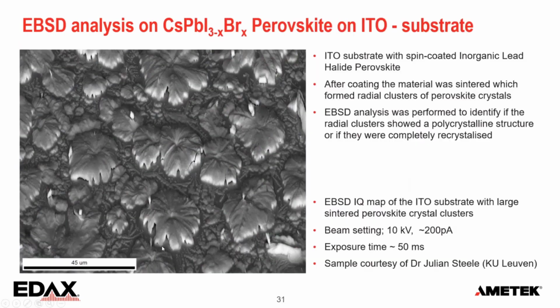Now, another one, this was a little bit more tricky. This is an ITO substrate with fibers of inorganic lead halide perovskite on top. And then it was sintered. And during the sintering, these fibers are merged, they're fusing, and they are producing these flower-like structures. You can see a radial microstructure with a center with all the points going outwards. It even looks a little bit like dendrites.